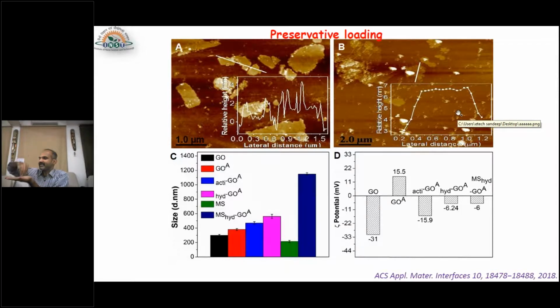Okay, so AFM is a tapping kind of characterization. It is like you are touching and seeing what the material is. As you can see in the top left, this is the pristine graphene oxide without conjugation, and it is showing 3 nanometer thickness. Which means approximately 6 to 10 sheets are there, because each sheet is about 0.3 nanometer, right? So with 3 nanometers, it should be approximately 10 sheets.